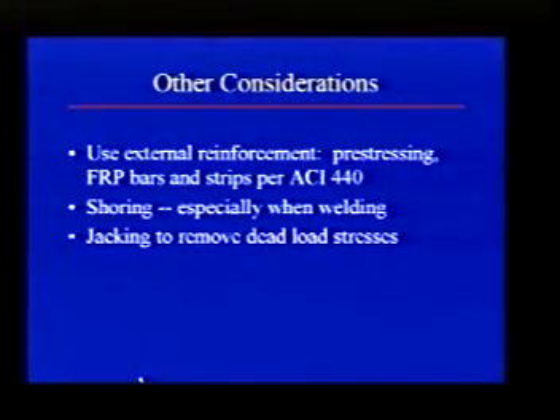Another consideration is shoring. If you have horizontal elements or vertical elements and you're welding those reinforcing bars, you really have to be concerned, because the yield stress of the reinforcing bar will be about 1/2 its capacity when the bar reaches 900 degrees Fahrenheit, and it will reach that when you're welding on it. Therefore, your capacity of the structure can be dramatically reduced if you only have 2 reinforcing bars present. You're welding on one of them, you have a much reduced capacity. If you have dozens of reinforcing bars, you're welding on one of them, you don't need shoring. So just be very concerned about shoring needs.